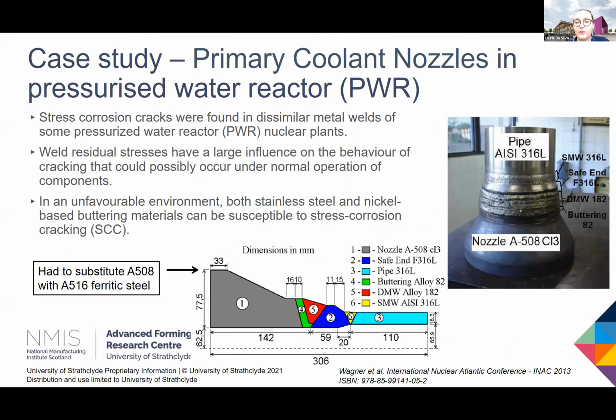So focusing in on how RFW could be applied in nuclear, we'll look at a case study of the primary coolant nozzles in pressurized water reactors. And I've got two example schematics from a paper by Wagner et al. in the International Nuclear Atlantic Conference from 2013. In this paper, they found that stress corrosion cracks were forming in the stainless steel side and some of the nickel alloy buttering elements.